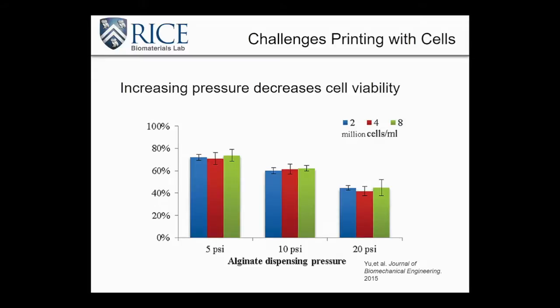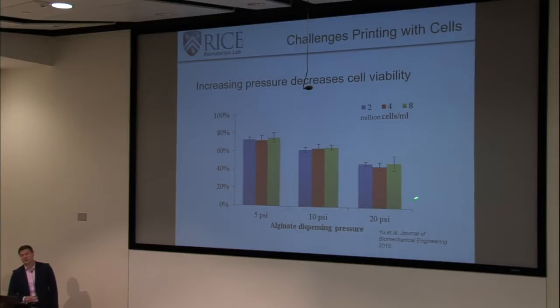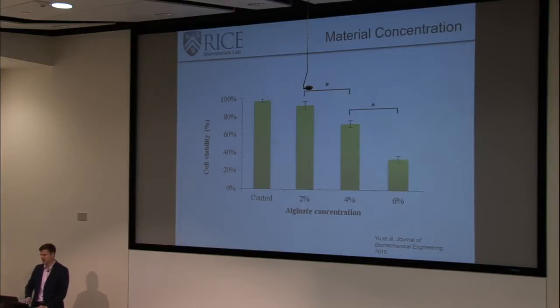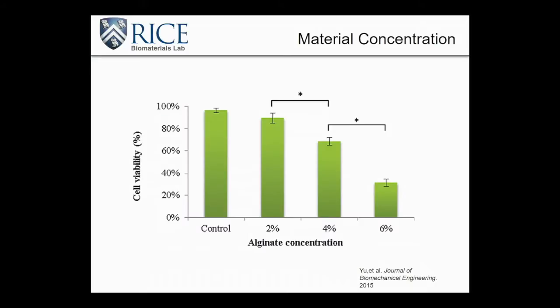If we compare the concentration of cells, then, for instance, with the pressure that we're dispensing cells, you can see that with higher pressures, as we would expect, we greatly decrease the viability of cells. So even though we're increasing these cell concentrations to pretty significant amounts, the largest reduction of cell viability is seen by altering the dispensing pressure within our bioinks. We also can see that the concentration of the bioink, which I haven't talked about too much, will impact the viability of cells pretty significantly.